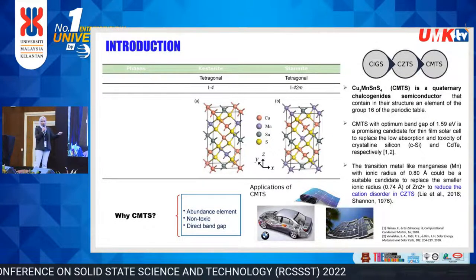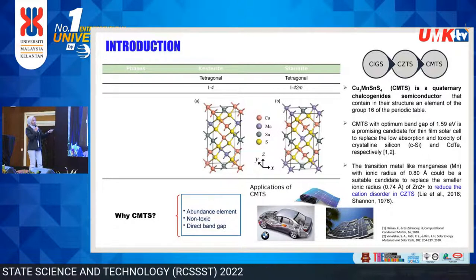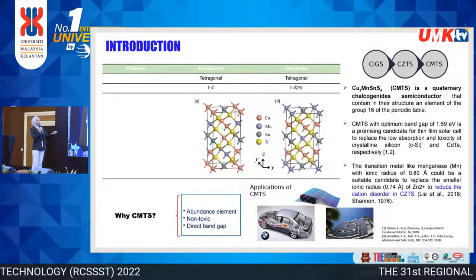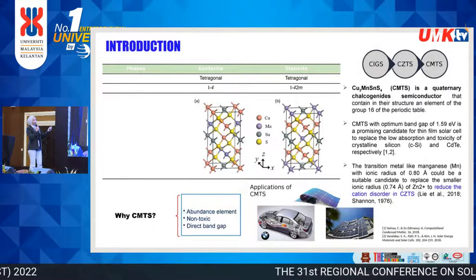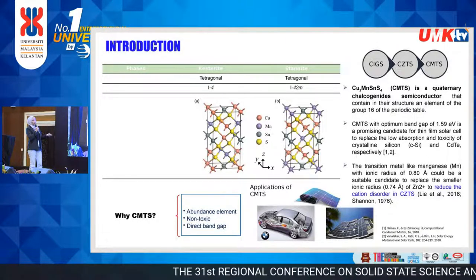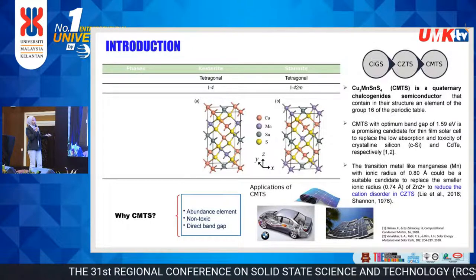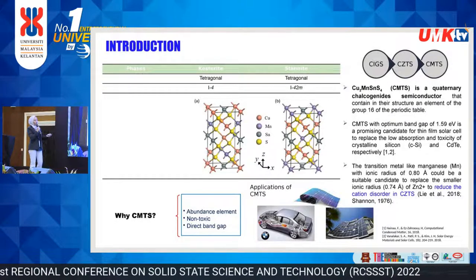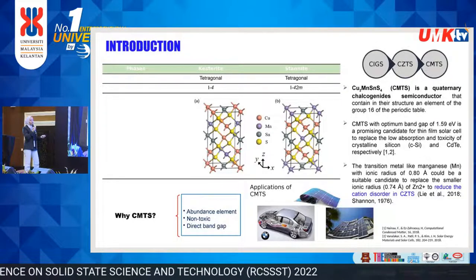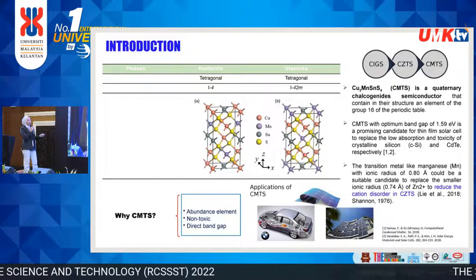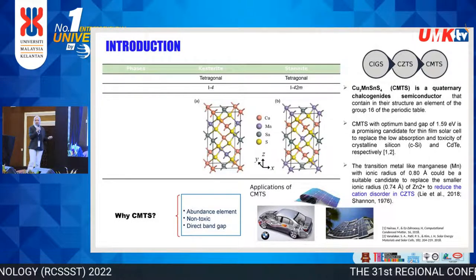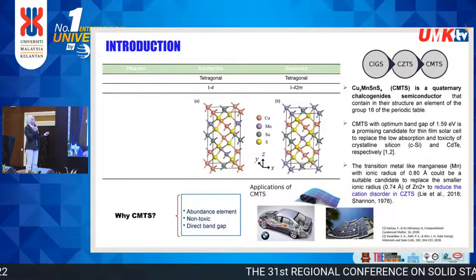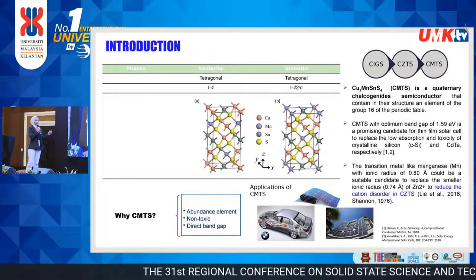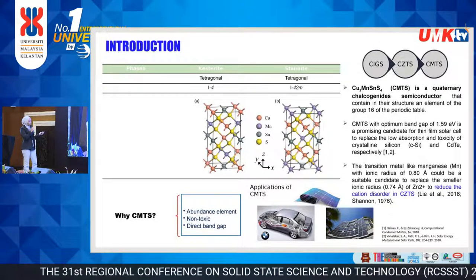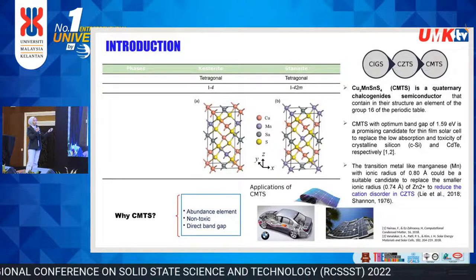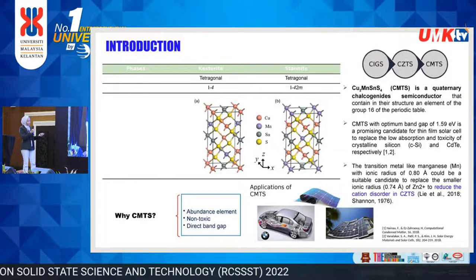However, due to some drawbacks of zinc in the CZTS material, I propose to substitute the zinc with manganese, whose ionic radius of 0.80 angstrom could be a suitable candidate to replace the zinc 2+ and to reduce the cation disorder in CZTS. So, why CMTS? It is because the CMTS contains abundant elements and is non-toxic compared to the CIGS and cadmium telluride.